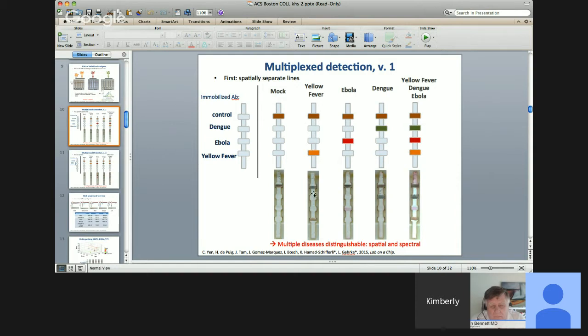So, for example, if we run a yellow fever sample through here, we should get a hit on this position only and not here, and that hit, the band, should be orange. If we do it for Ebola, we should get a hit here, but not here, and it should be red. And then dengue, it should be only here, and it should be green. And if we have all three present, we should get it to light up at all three positions, and they should be all different colors.